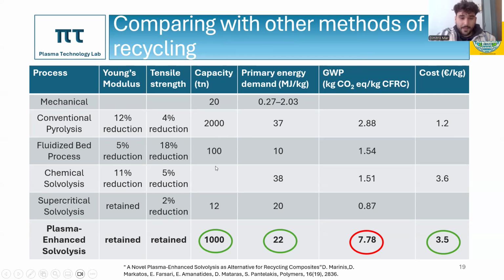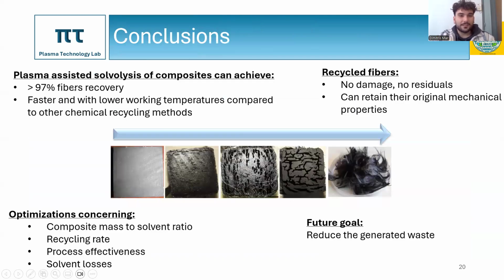Other than that, the capacity of the plasma enhanced solvolysis is already really high, so it can be helpful in a potential scale-up. Concluding, plasma-assisted solvolysis can achieve over 97% fibers recovery faster and with lower working temperatures compared to the other chemical recycling methods. The recycled fibers showed no damage and no residuals, and they can retain the original mechanical properties. We had some optimizations concerning the composite mass to solvent ratio, the recycle rate, and the process effectiveness, and the solvent losses. Overall, our future goal is to reduce even more the generated waste.